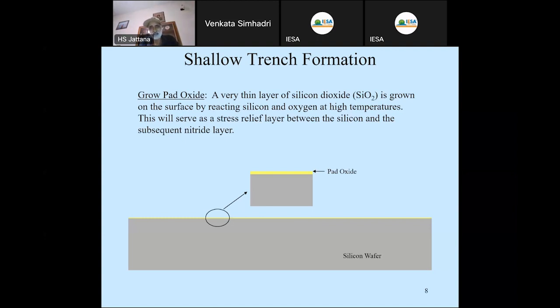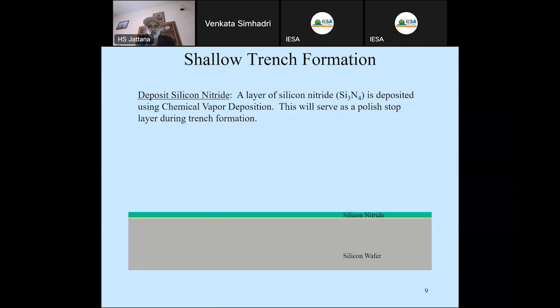The oxide thickness again depends on the process. If you have a small process design, it's very small, say around 200 angstrom. So there is this layer. On top of this layer, I will deposit nitride. I cannot deposit silicon nitride directly on silicon because of the mismatch of the two films. So this acts as a stress relief layer between silicon and the silicon nitride. And it becomes a very good interface. So I have deposited silicon nitride also on this.